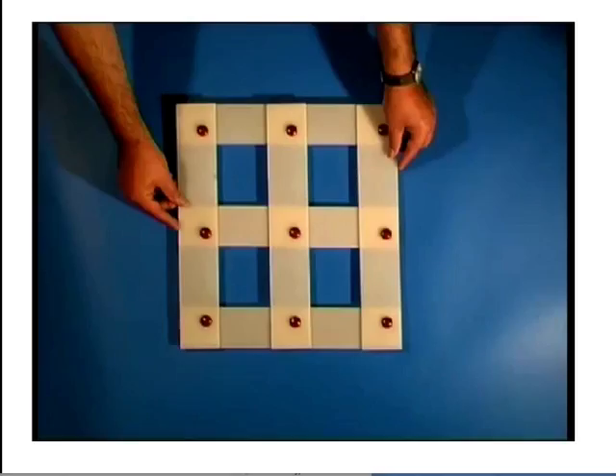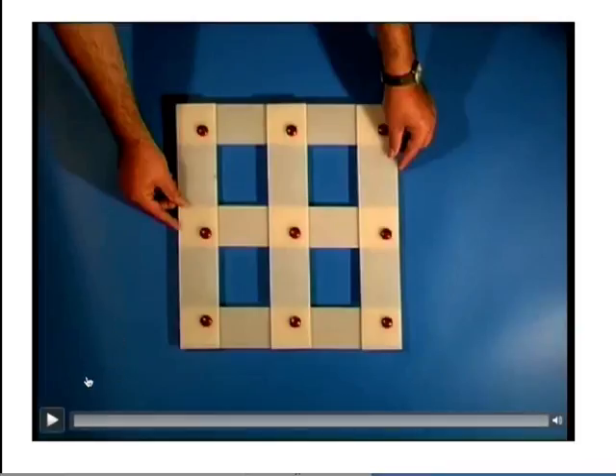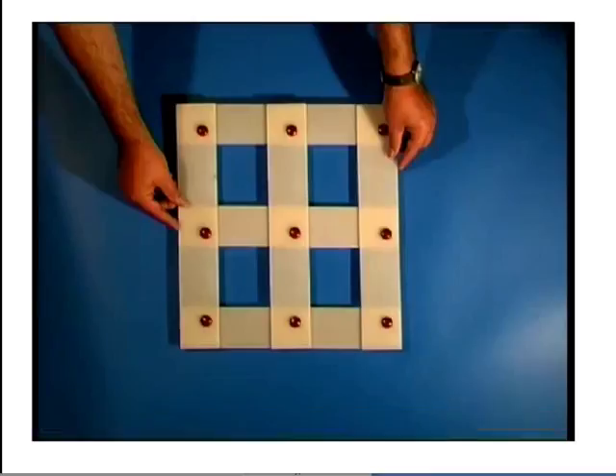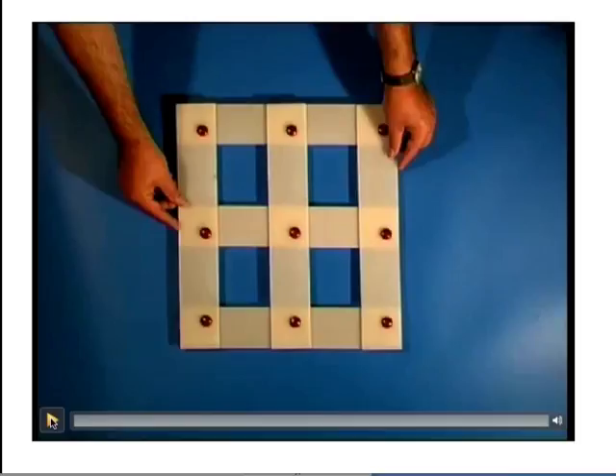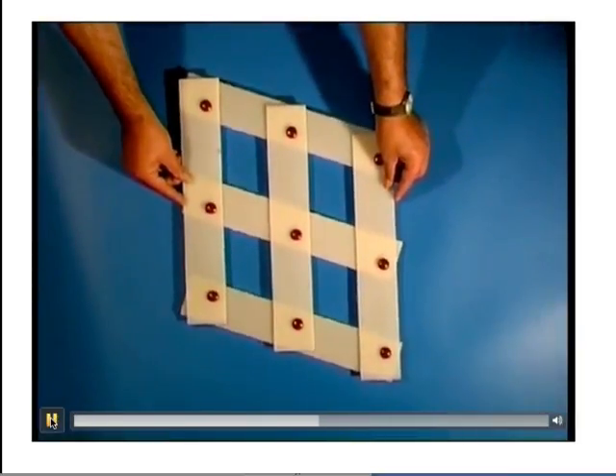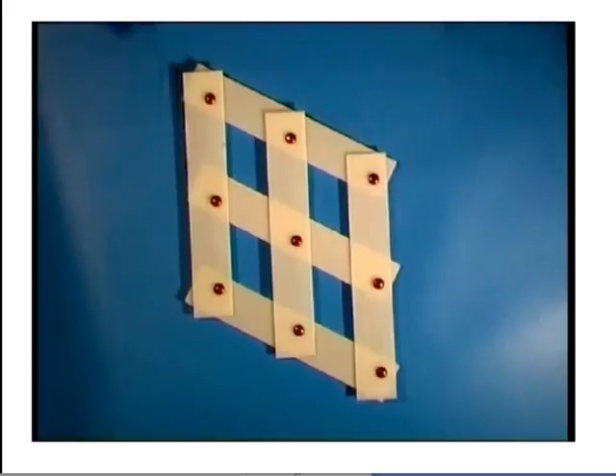Okay, so let's assume we've got a square lattice, and we want to change the pattern in which the atoms are arranged without breaking any bonds, because we do not have diffusion. So all near neighbors must be preserved. We can do that by a physical deformation. You can see that we've changed the pattern in which the atoms are arranged without breaking any bonds. But the consequence of that is that the external shape of the crystal has changed. So in this case, it's a shear deformation.